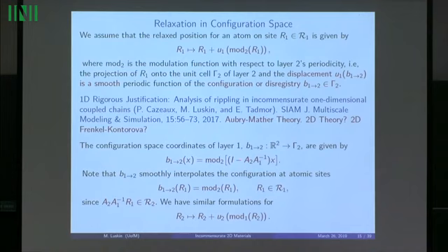What that says is, when you move in space, the speed of change in configuration space is theta. You move size 1 in real space, then the change in configuration is going to be of order theta. And that's telling you too that the Moire scale is going to be 1 over theta. Okay, so we have a similar formulation